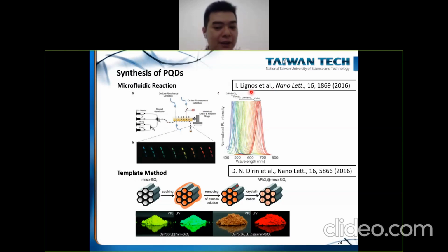And also there are other methods such as the template method. You can use mesoporous silicon dioxide with a specific pore size, and then you soak it in your precursor, and then when you remove the solvent, the quantum dots will automatically form inside these pores.